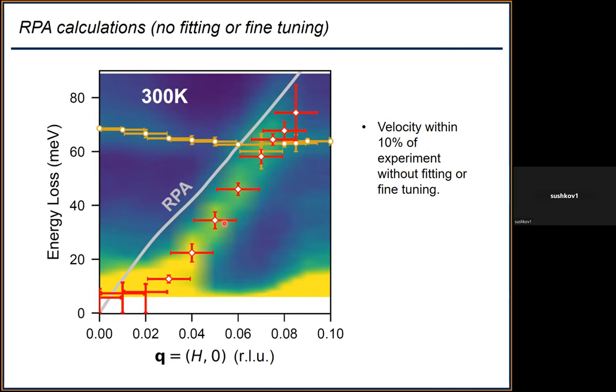Optical is transverse. It's an odd parity mode, the optical one. It could just be a transverse mode. Yeah, actually, it's probably a transverse mode. Am I correct that because you have at least three different atoms in a unit cell, you would expect the number of optical modes to be larger, not just one? Yeah, there's a bunch of them. So only one of them is visible in this experimental setup. Yeah, well, if you scan to higher energy, there's more. But if you add up the number of clear modes we see, it doesn't come out to three times the number of atoms minus three.